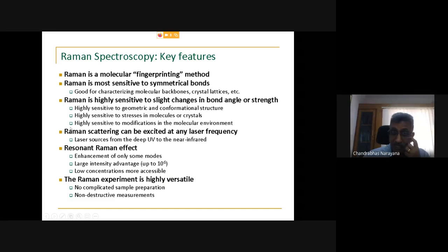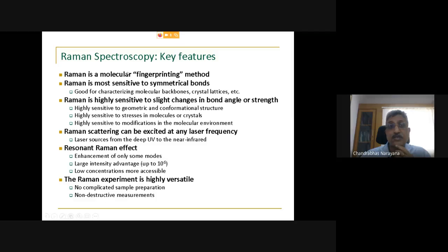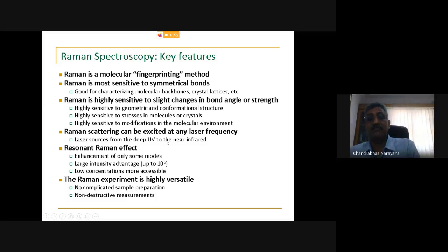Now, one of the biggest advantages is that Raman spectroscopy is a very, very useful technique because it is a fingerprinting technique. You can easily find out the molecular structure, because if I have the same group, then I know that the Raman spectra will look similar. It is highly sensitive to symmetric bonds, which I showed you, and it is highly sensitive to the bond angle and bond strength. So we can find out the geometric conformation of the structure, stresses in the molecules, and sensitivity of the molecule.